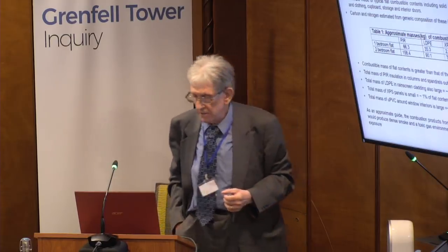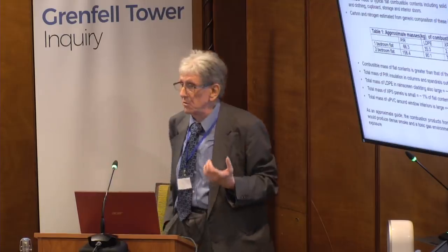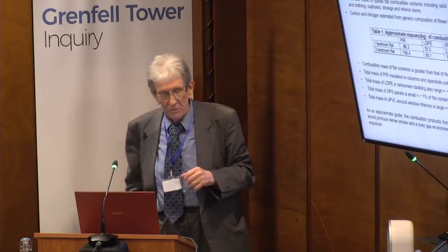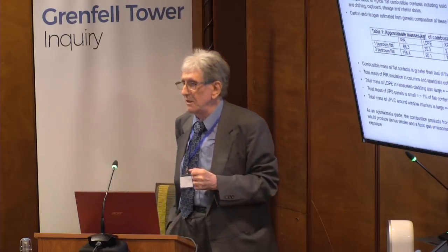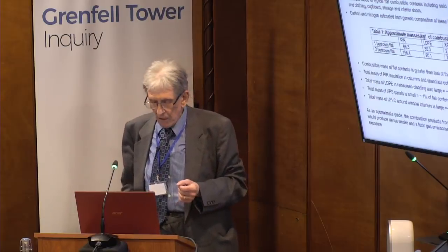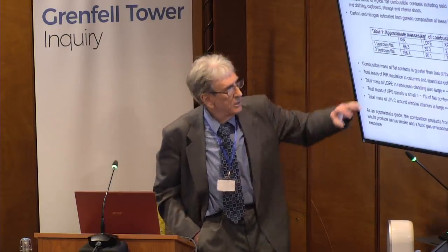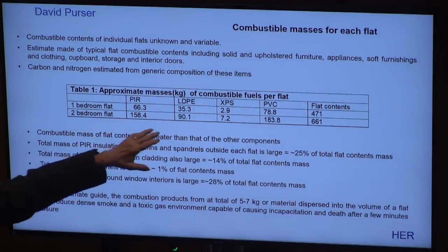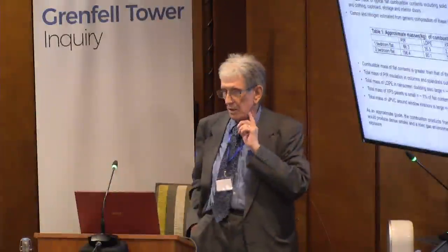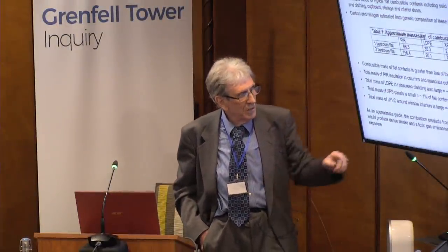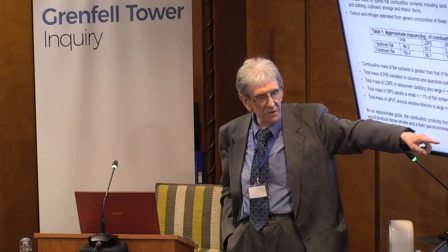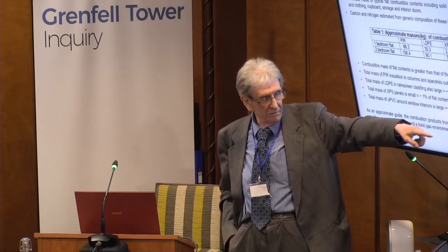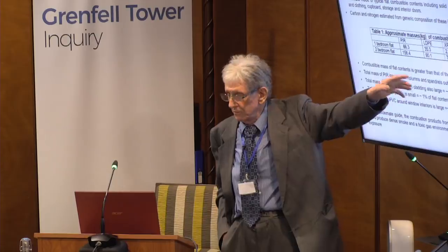When we come to the flat contents, this, of course, is by far the largest total item. So I would say that the flat contents is going to be about 660 kilos of contents. But what this shows is that the PIR and the LDPE and the PVC are quite large, significant amounts in the context of, for example, a total flat fire load. And I keep going back to my 5 to 7 kilograms burning in a flat is enough to cause a hazardous atmosphere, right? And we're talking about hundreds of kilos here.